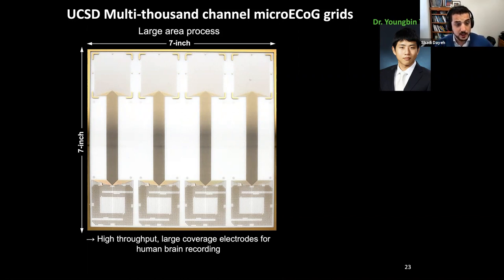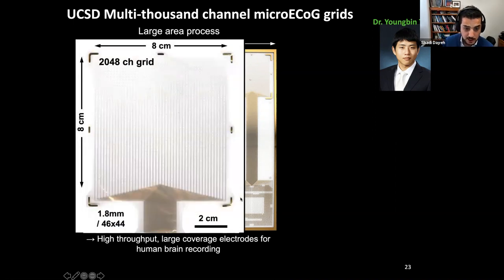Now to do that, we basically need to make the electrodes on large substrates. So we use the glass substrates that are typically used to make masks. These are 7-inch plates, and we manufacture the devices on top of these plates. Here you're looking at four copies of the 1024 grid. On top are the contacts. On the bottom, these contact sizes are determined by the LGA matching socket.